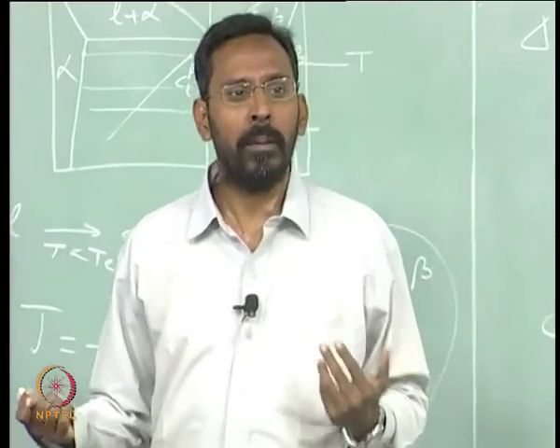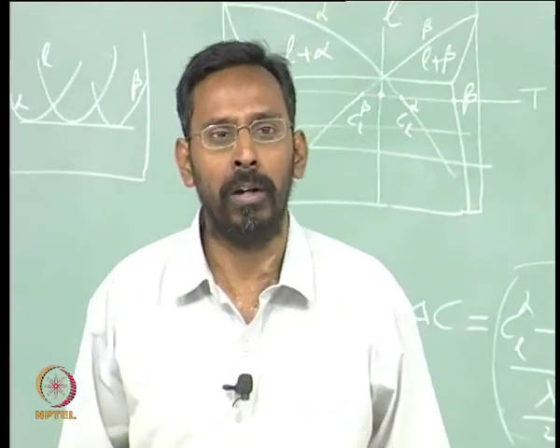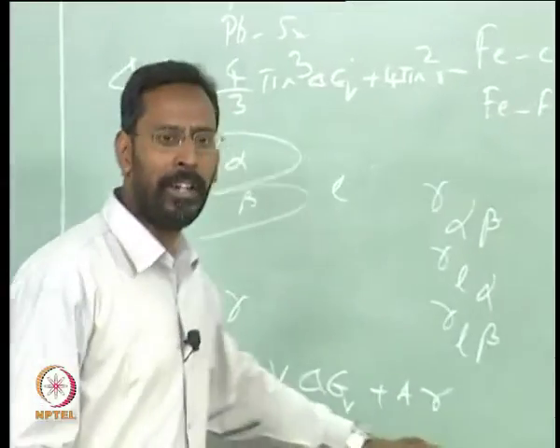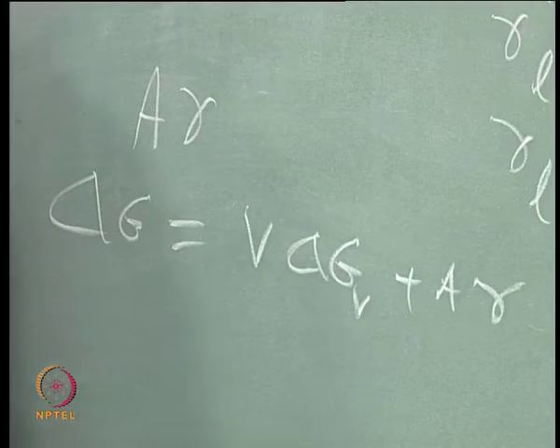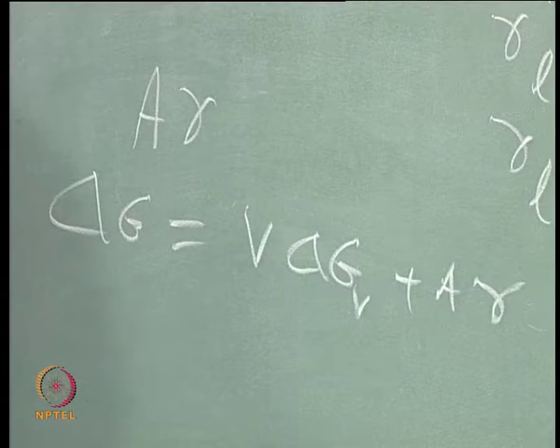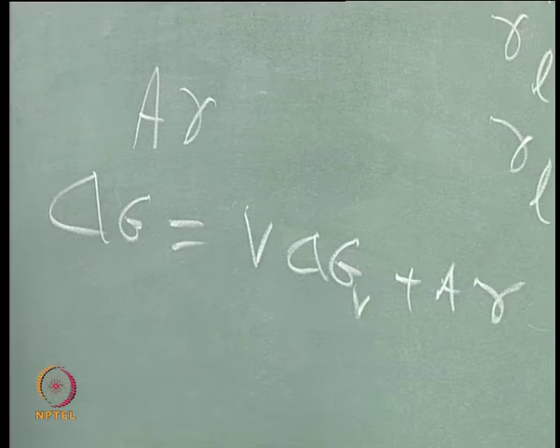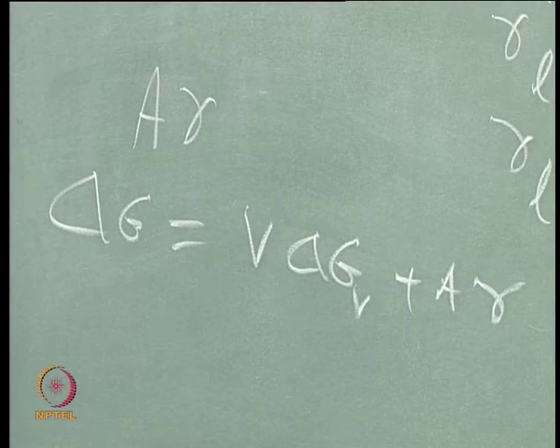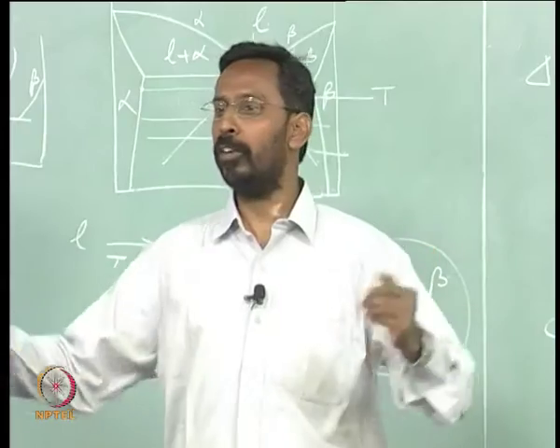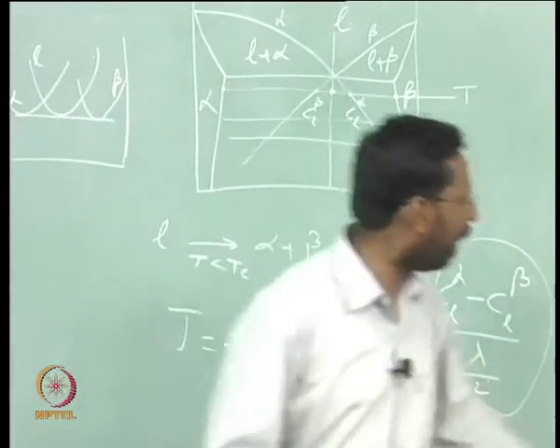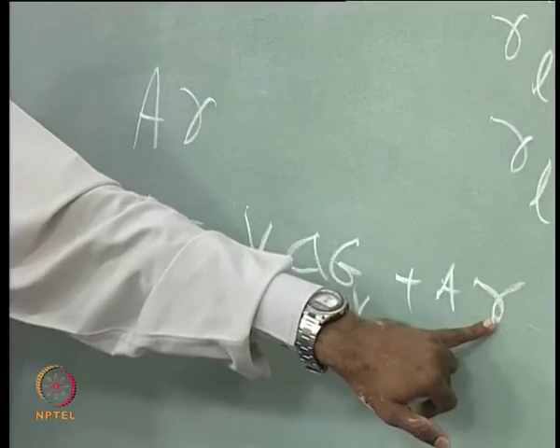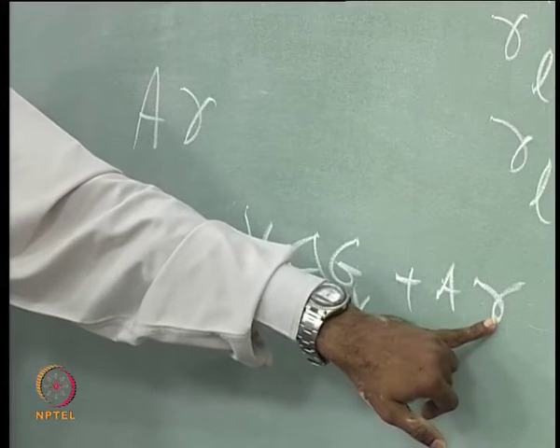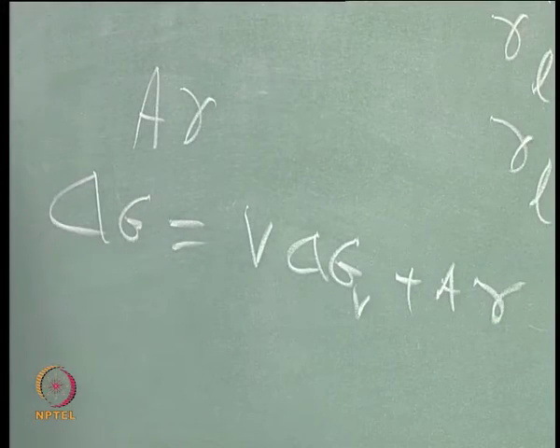The liquid wants to become a solid at as small an undercooling as possible. So it will choose - for example, if it is a pure metal solidifying, it has no choices of interfacial energies, there is one single solid nucleating out of that. There also it will search for any heterogeneous nucleating sites. The moment there are heterogeneous nucleating sites, the liquid is very happy, because this gamma is very small there.